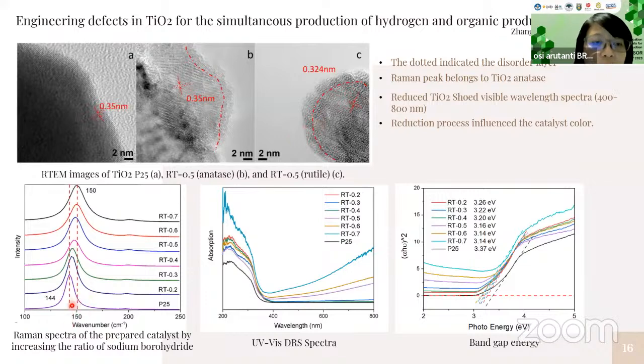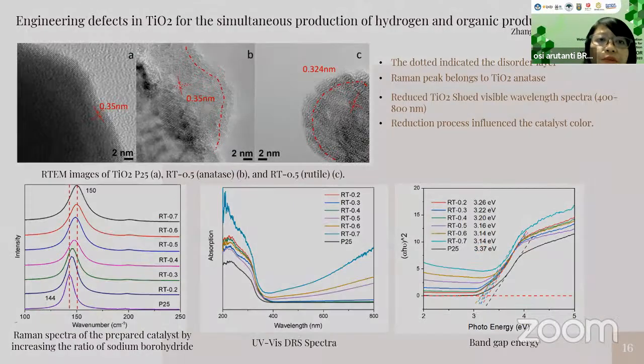The Raman analysis result is also similar to the previous one. The titanium dioxide peak shifts a little bit due to the reduction process, by increasing the concentration of sodium borohydride. And this is from the UV-vis DRS spectra. The wavelength increased, and this is the energy band gap. The energy band gap decreased a little from 3.37 down to 3.14 electron volts.